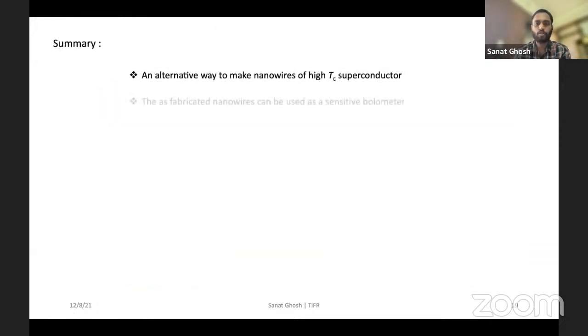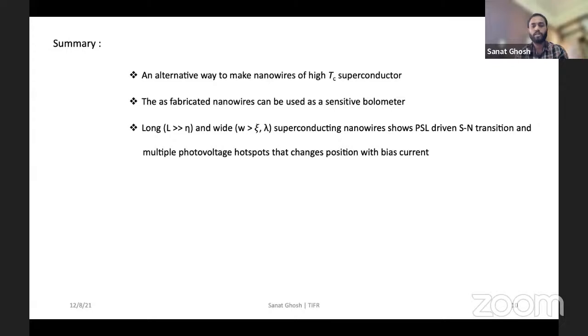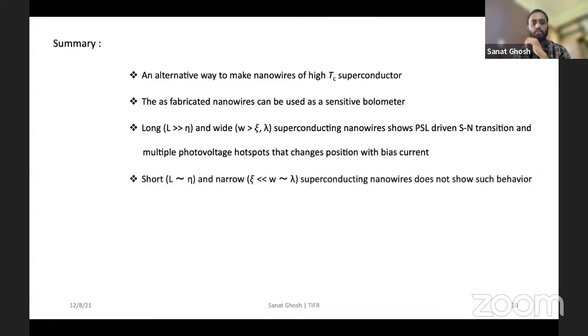So with this, let me summarize. We have figured out a way to make superconducting nanowires of a high temperature superconductor, and shown that this can be used as a sensitive bolometer. For longer nanowires, there are phase slip lines driven superconducting to normal state transitions, and we image those spots where the photovoltage is maximum along the nanowire length, and those spots change position when you change the biasing current. Whereas in the shorter version of the nanowire, we don't see such behavior. So with this, let me thank you. If you have any questions, you can ask.